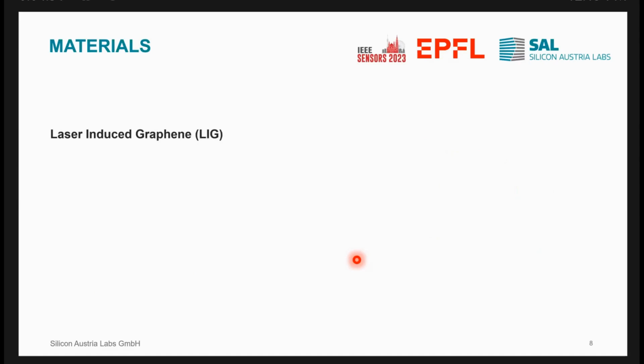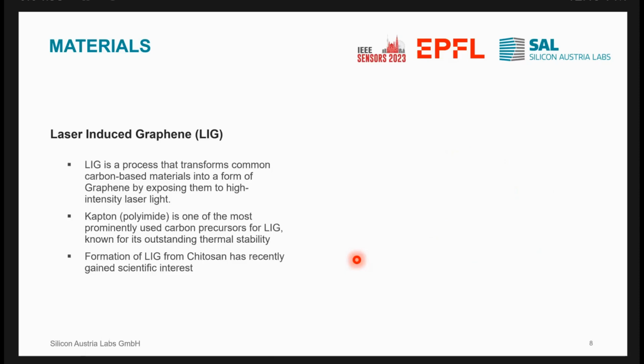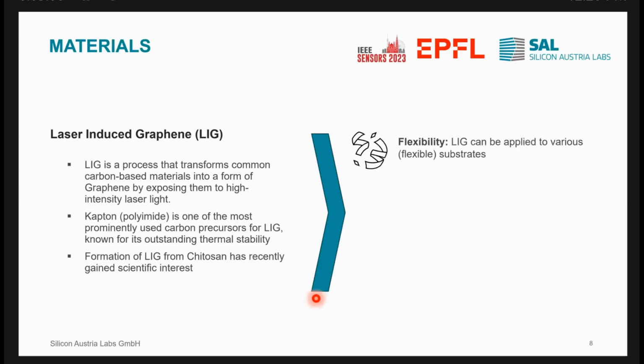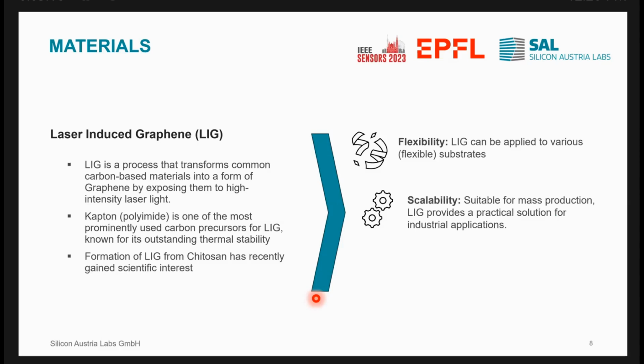What I think not every one of you might be familiar with is laser-induced graphene. So laser-induced graphene is a process that transforms common carbon-based materials into graphene by exposing them to high-intensity laser light. Basically, LIG can be fabricated on any carbon precursor, and Kapton is one of the most prominent materials for the fabrication of LIG. And recently, also the formation of LIG from Chitosan has gained scientific interest. So to summarize, LIG can be applied to various substrates. A big bonus point is the flexibility. The fabrication of LIG is scalable as it is suitable for mass production. And it can be considered as environmentally friendly as there is no additional material added, as just the existing material is converted to graphene.